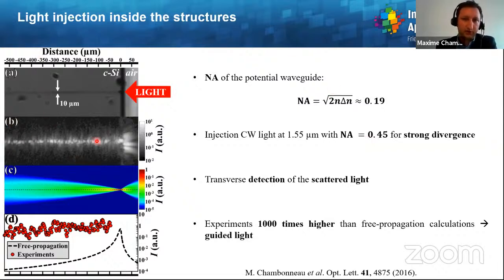And from the scattered light picture here, one can clearly see that some light has been guided, especially when you compare to the linear propagation calculations. So this is indeed the comparison between B and C. And you can see that in the experiments, there is more light than normally if you consider only free propagation inside silicon, meaning that part of the light has been guided. Especially, this is a semi-log scale, which means that the experiments are 1000 times higher than the free propagation calculation. So in the end, light has been indeed guided with high losses. I will come back to this afterwards, but still, it's a first step.